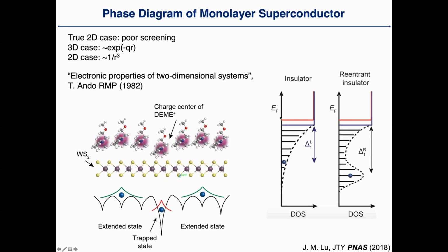So the physical background of the system is like this. We have an insulator, and then we have the band edge, like a normal semiconductor. And when you put carriers inside, you start to feel this band tail and start to enter the real band, then become a metal, and if you go further, it becomes a superconductor. And then, if you gate very much, when this kind of trap states start to form, the donated carriers will actually be trapped by the trap state. And when all the carriers are trapped by those trap states, the system again becomes very, very insulating.